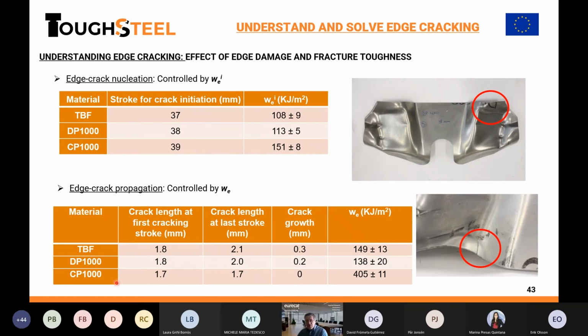So here is for the same materials, the length of the crack at the first stroke that we see a crack appearance, and this is how the crack grew in the forming tests. You see that the cracks that grew more were the ones having less fracture toughness, lower fracture toughness.